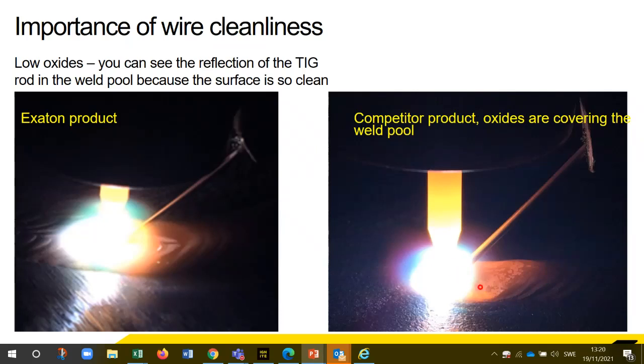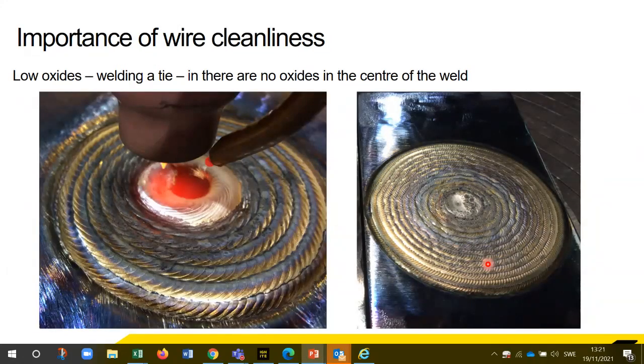On a competitor's product here, we see there are oxides. I'll not say slag, but certainly oxides in there, and so you can't get the same effect. You don't have the mirror finish to enable that to be seen. And the last slide that I have is showing the welding of a tie. If you've got a buildup of black soot, oxides, lubricant on the surface of the wire, then you end up with a very big black scaly oxide pool. Essentially, we don't get that, but this will absolutely illustrate it.